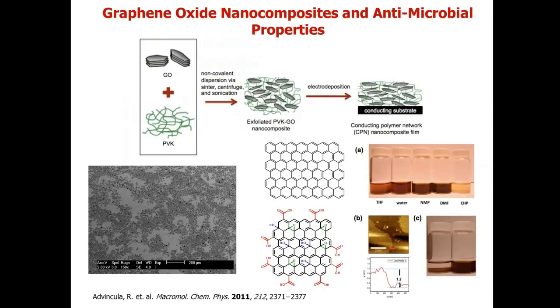Here, we have shown that we can disperse them, of course, with PVK. By TEM, you can see the platelets have very good polydispersity. Here again, the solution or solvent qualities of the dispersed graphene oxide.